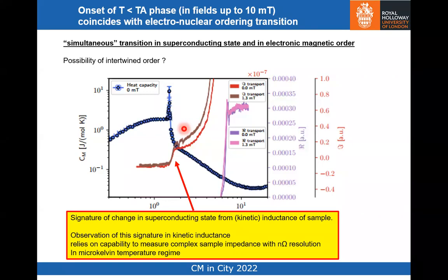This is using the language that we have at this transition. We induce a spatially modulated electronic moment that I'm loosely referring to as spin density wave order. But what we're pointing out here, again, we saw it at the beginning, is that this is certainly in zero magnetic field, the transition in the superconducting state and in the electronic magnetic order is simultaneous, and that raises the possibility of intertwined order.